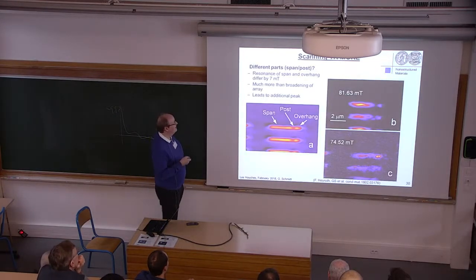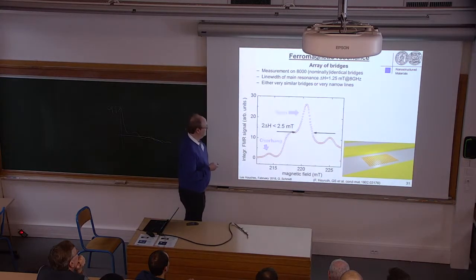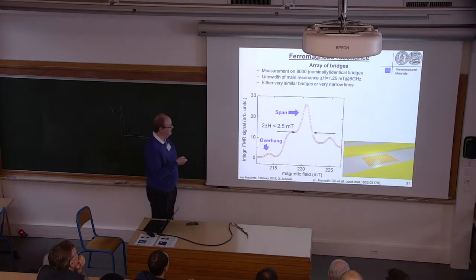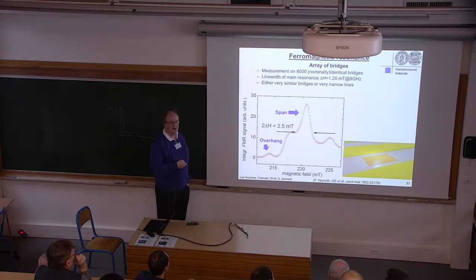And then you have the different parts of the bridge. You have the span and the post and the overhang. So this is kind of a topology image. And you can see that here you have a variation of about 7 millitesla between this resonance and that resonance. And interestingly, this is what you see. Here you have the main resonance, and here you have something 7 millitesla apart. So this is actually the overhang, which you see.